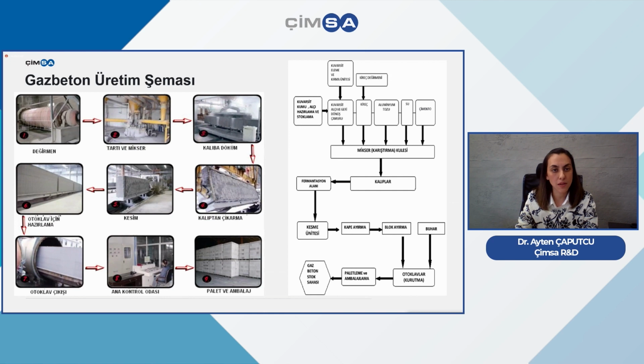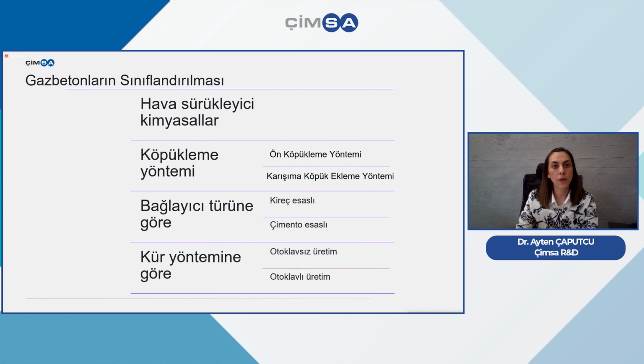When we look at the production phase, you see a mill here, and the materials are being ground. And when you look at the chemical composition, it is essential to be optimized and measured. It is brought into a homogeneous structure. These are being molded, and you see the caking process. After taking it out of the mold, with the automatic cutters it is possible to slice it and send it to the autoclaving unit under high pressure and heat. It is being cured, and the autoclaved material is being controlled, packaged, and transferred to users.